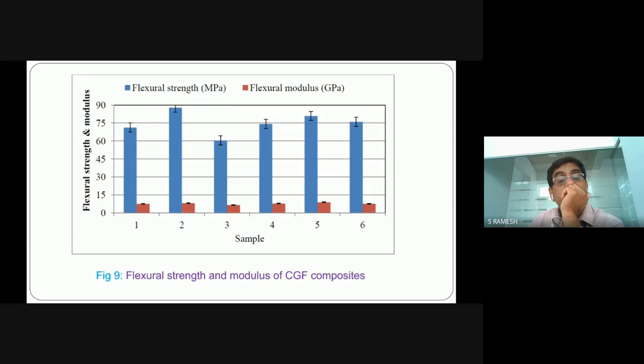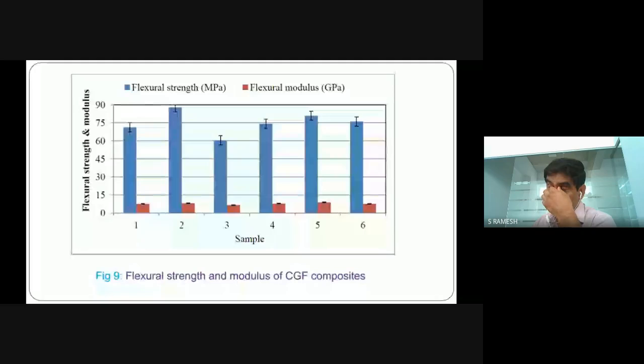When we go for flexural modulus, it's nearly 6.55 gigapascal to 8.86 gigapascal. The flexural modulus is normally a bending modulus. It's an intensive property, a ratio of stress versus strain in flexural deformation. The flexural modulus is the tendency of a material to resist bending.